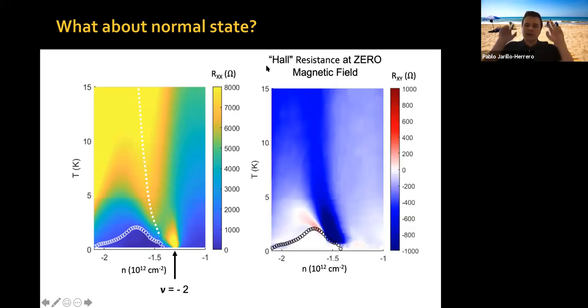If you measure Rxy, so it's not really a Hall resistance measurement, it's just an Rxy measurement at zero magnetic field, here's what you measure. You see there's a region of very strong Rxy, even though there is zero magnetic field. And I just take this line and put it here without any adjustments, it coincides perfectly with this region where we have a resistance maximum here.